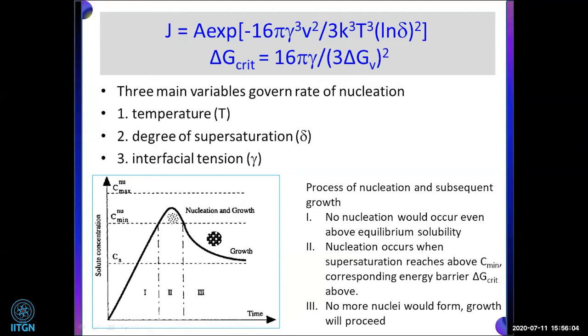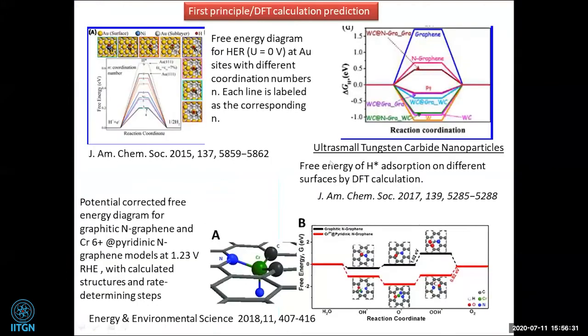When we do this, we get monodisperse nanoparticles, and using a surfactant, we can make the nanoparticles two-dimensional or one-dimensional, say nanosheets, nanorods or quantum dots. Then we have to follow the nucleation and growth process. In the growth process we have two kinds: one is focused growth, and one is unfocused growth. After following all this, we can make nice nanoparticles, and that gives us a lot of good examples.